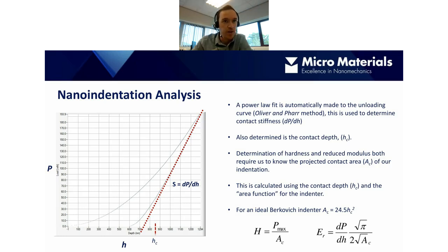You can see for this particular indent, hc will be around about here. It's basically in between the maximum depth, which is almost 1.3 microns, and the residual depth, or the plastic depth, which is about 600 nanometers. The determination of the contact depth depends on the model used, but in the Oliver and Pharr method, it's the maximum depth subtracted by another term, which is the load divided by the stiffness, multiplied by a constant called epsilon. This is dependent on the geometry of the indenter. For a Berkovich indenter, the epsilon constant is 0.75.